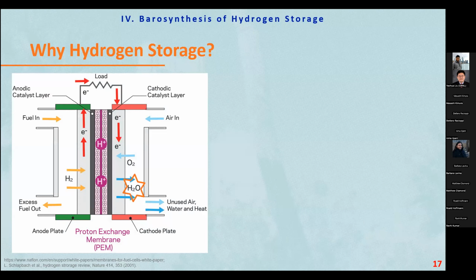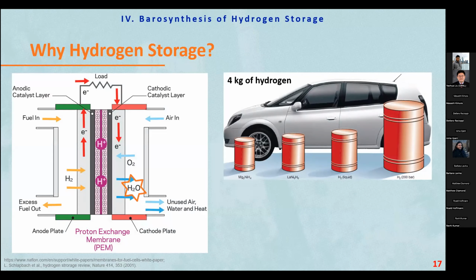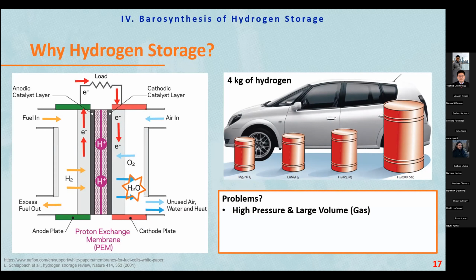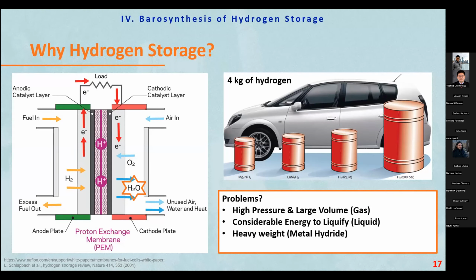But the problem is that hydrogen is a very hard material to store because it is a light element, and also very small. This is 4 kilograms of hydrogen stored in this container, and this is just a size comparison, when you have the hydrogen as a gas and it needs a big storage. The problems are the high pressure: we need high pressure and large volume to store gas. That's a potential danger. And we need considerable energy to liquefy hydrogen, and it's not efficient. We also have a heavy weight problem for metal hydride storage, and in this case the dehydrogenation temperature is also very high.